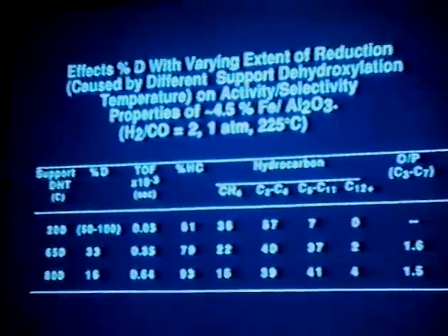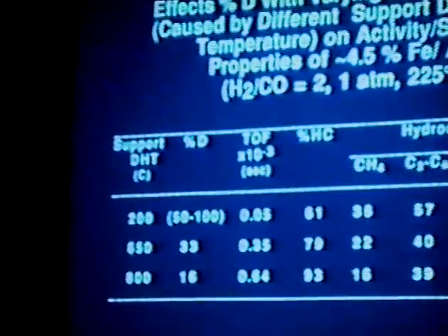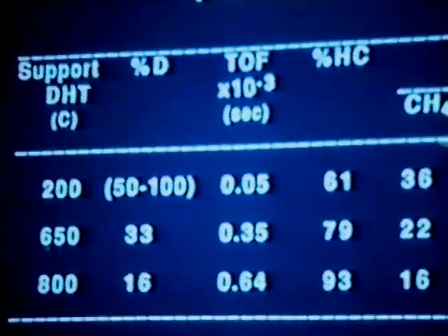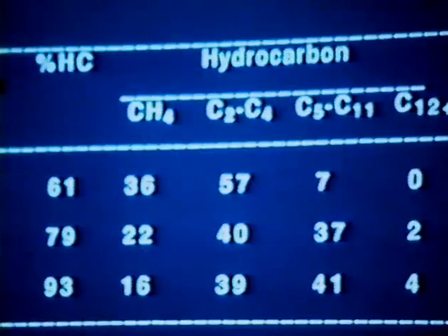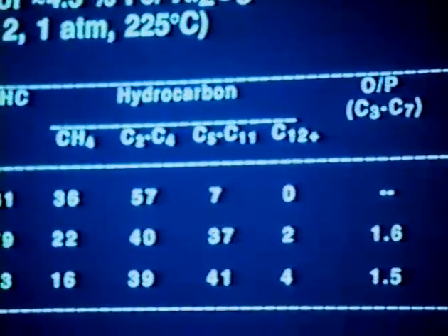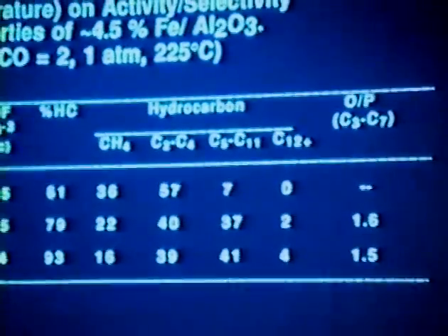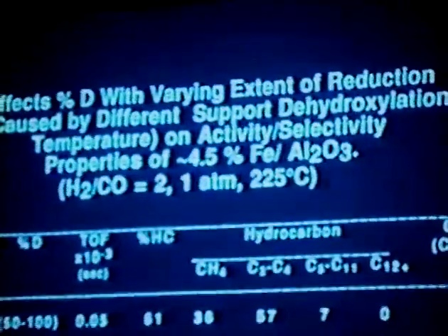But now, when we look at the second set of catalysts, where the dispersion was varied, which was also accompanied by the variation in extent of reduction, we find an order of magnitude increase in activity with decreasing dispersion. And hydrocarbon selectivity has increased with decreasing dispersion. Sorry, there is higher selectivity for higher hydrocarbons on poorly dispersed catalysts, and vice versa for the well dispersed catalysts. These are the typical observations for structure sensitivity on supported metal catalysts.